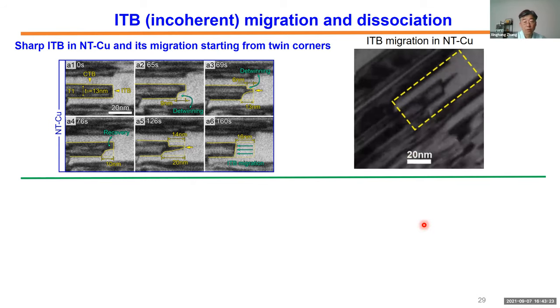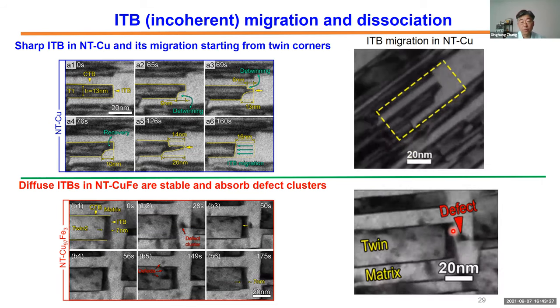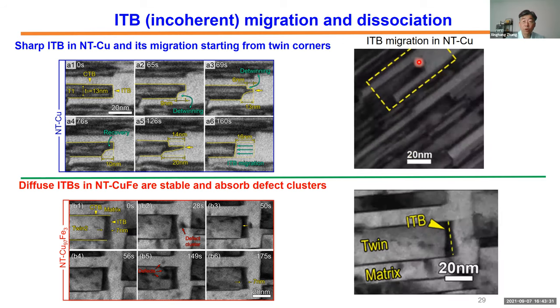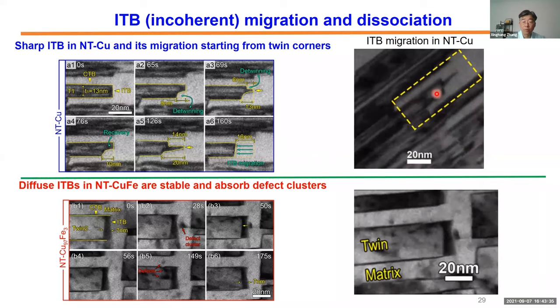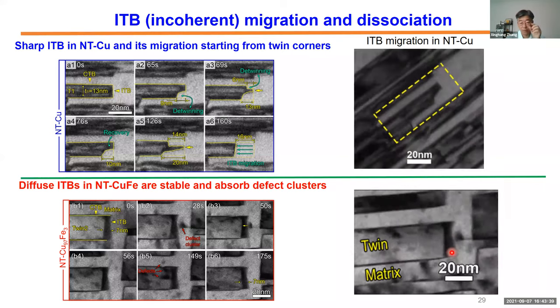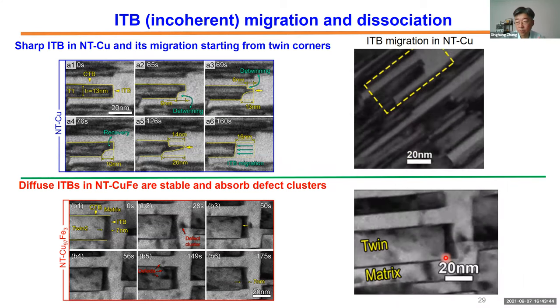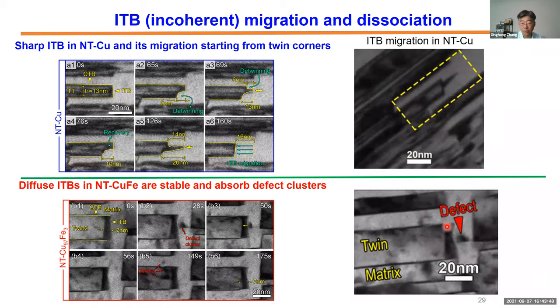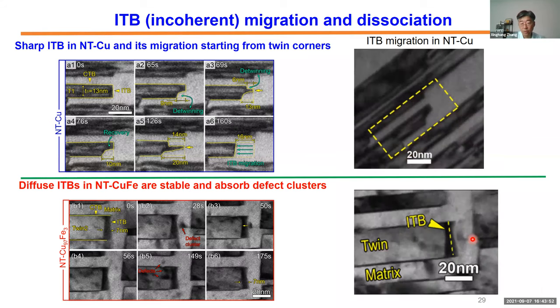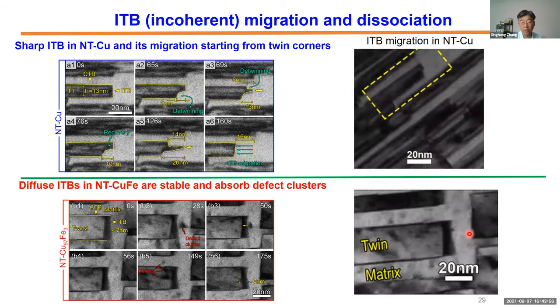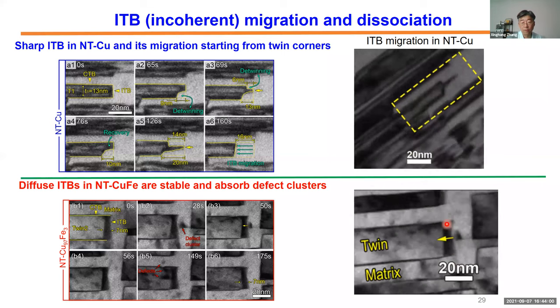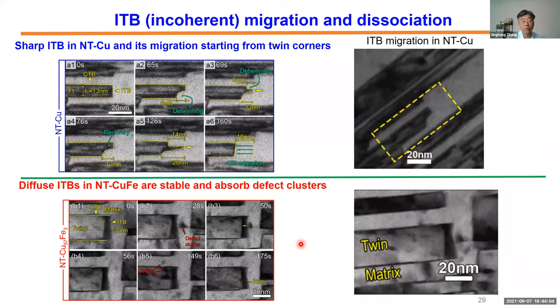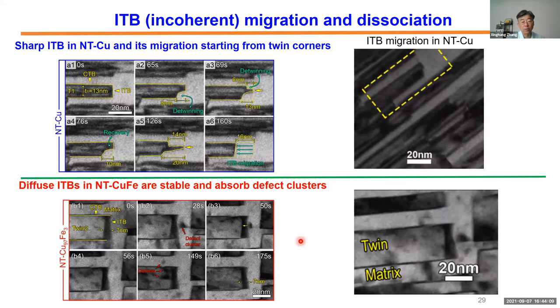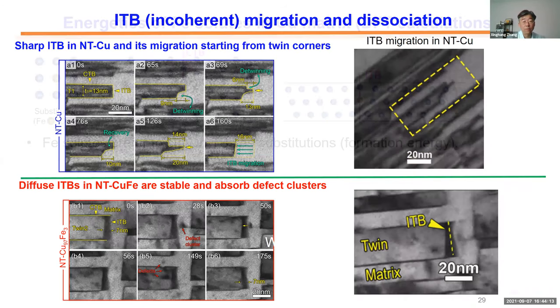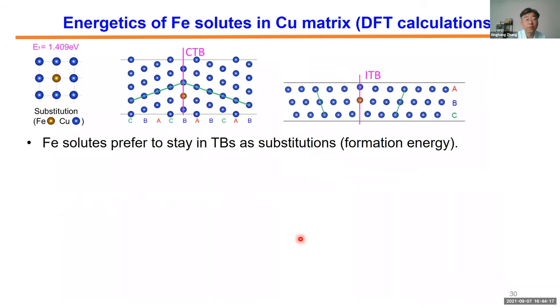So now if you look at the same thing for nanotwinned copper iron, things are quite different. We find out these twin boundaries, they are not as sharp as twin boundary in copper. These boundaries instead after radiation become blurred, so have a darker band at the end of this twin boundary. So this is something we call, later we're going to see, this is ITB. And not only they stabilize twin boundary, but they also capture some of these triangular defects. And these triangular defects are so-called stacking fault tetrahedra, SFTs. So they can be captured or gradually absorbed by this blurred incoherent twin boundary. So that is very different between ITBs in copper versus in copper iron. So let me move on and try to explain how do we explain this phenomenon? Why would iron help us to stabilize twin boundary?